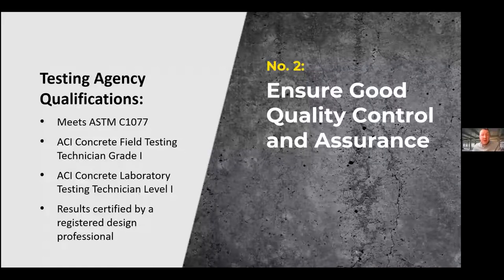If these test results are constantly showing lower strength, then the only way to overcome them is to increase the overdesign, which generally raises cementitious content and ultimately impacts the global warming potential of your mixes and the sustainability of your project.